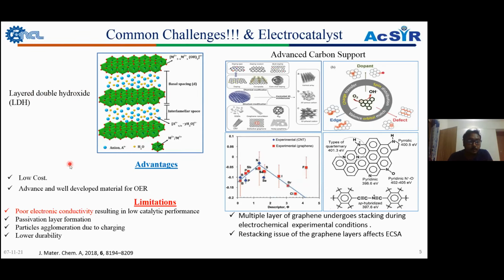So the advantages of the layered double hydroxide are that it is very low cost, and it is a well developed material for the oxygen evolution reaction. But the limitation associated with layered double hydroxide materials is poor electronic conductivity. It is only a double hydroxide, so there are enough active centers, but the conductivity is very low. And the second thing is passivation layer formation, because in oxygen evolution conditions, with the potential and the pH, both being harsh, there is a chance that after certain cycles a passivation layer forms, which can suppress the activity.